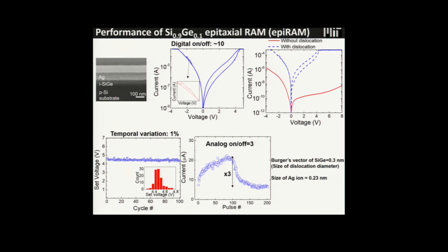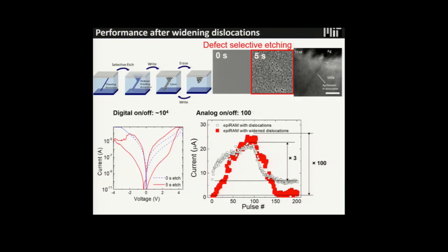But one thing we are not so happy with is the on-off ratio of this device. The on-off ratio has to be more than 100, but this on-off ratio is just 10. It's hard to emulate the human brain using this low on-off ratio. So there's another solution. Why is this on-off ratio so low? Because the Burgers vector of your dislocation pipe is just 1 atom in size. Then what's the strategy? It's just to widen the dislocation.